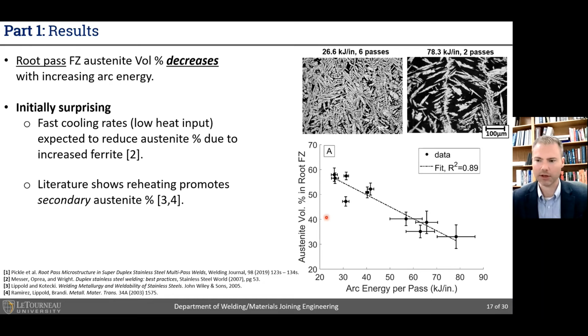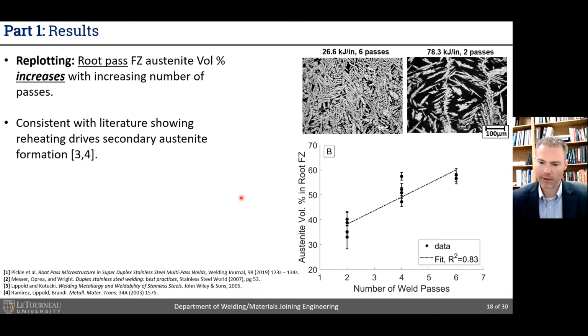We found almost a linear decrease, and we know from the literature, as I've already alluded to, that it's suggested that reheating is a prime driver for causing secondary austenite to form. And so this led us to hypothesize that perhaps that was the driver. When we looked at this in terms of the number of welding passes, it began to sort of fit within this prior known work. And you can see that as the number of welding passes increases, we see this increase in the percent of austenite in the root of the pass.